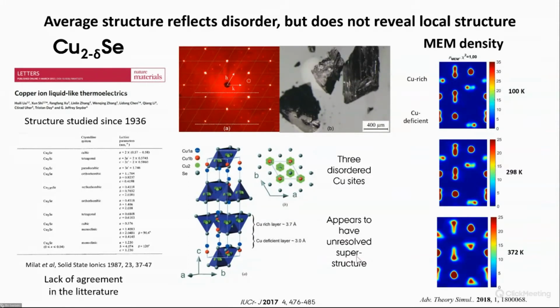But when we don't really know the structure, we can always do the maximum entropy method, which I also worked on since I was a student. Here you just divide the unit cell into voxels, and then you distribute the electron density under the constraint of the data and this maximum entropy. When we do this through the phase transition with the single crystal data, we see copper moving from the rich layer down to the poor layer, and in the end we get into this antifluorite structure, which is highly, highly disordered. This is where it's been studied a lot, this superionic conductor copper selenide.